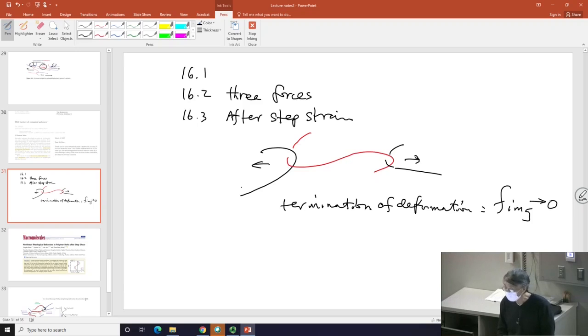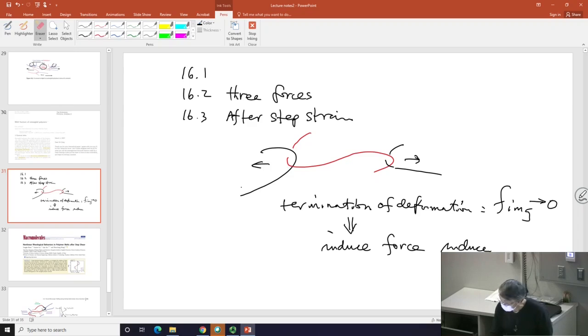If it's turned off, you necessarily will induce force imbalance. So even if you are still deforming, then the force imbalance may not have occurred yet. In other words, as long as this gripping force is larger than the building up retractive force, molecular deformation will continue.